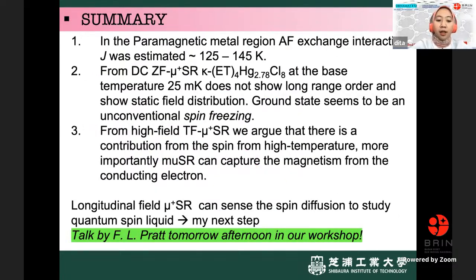So yeah, this is my summary. At high field, we confirm that there are antiferromagnetic exchange interactions, and from zero field μSR, there is no long range order for the chlorine sample, and the ground state seems to be a spin freezing because there is no muon spin precession. But it's unconventional because it started from the metallic state, which is strange, and then from the high field transverse field, we argue that there is a contribution from the spin.